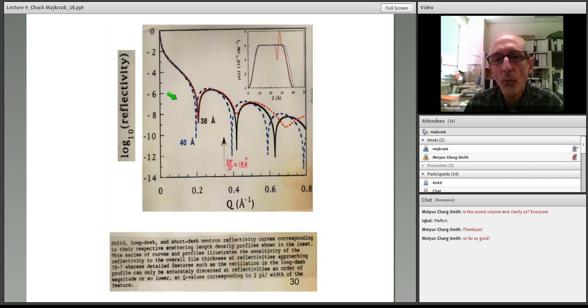But it also turns out for certain systems, like a thin film with a front and a back, that to get other quantities, for example, the total thickness of the film, because of this very strong interference between the front and back reflected components of the reflected beam wave function, the locations of these minima are very accurate indicators of the overall thickness.